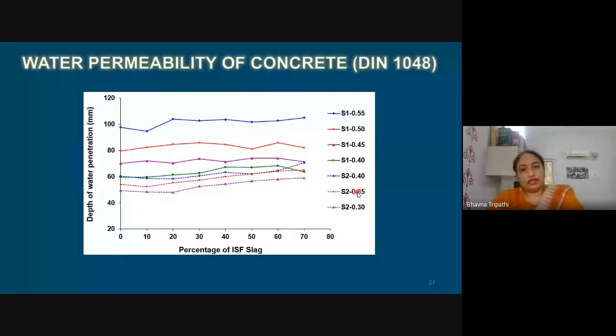Another test which we had conducted to establish permeability was DIN permeability. This is a destructive test. Earlier, both the tests on air and water permeability were non-destructive tests, which are widely used at site, not in India, but abroad. It is a sophisticated method. This one is more widely used, DIN 1048, and most of the laboratories also have DIN 1048. So when we test DIN 1048, all the specimens we can see are more or less comparable to control. There is no appreciable increase in permeability.